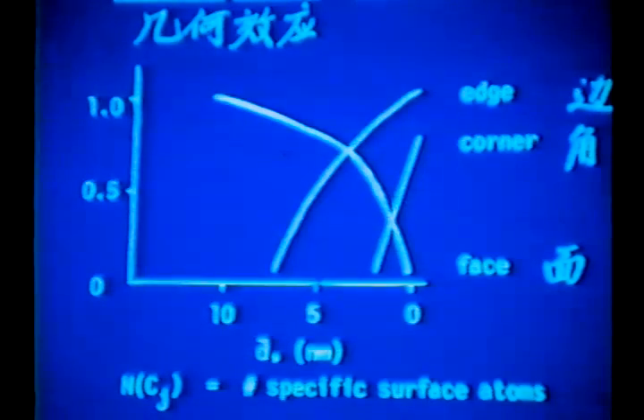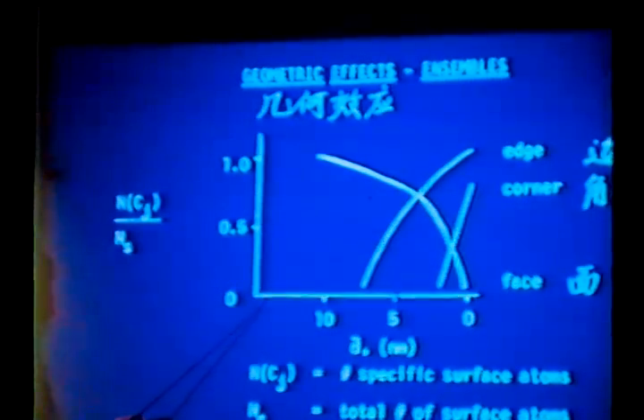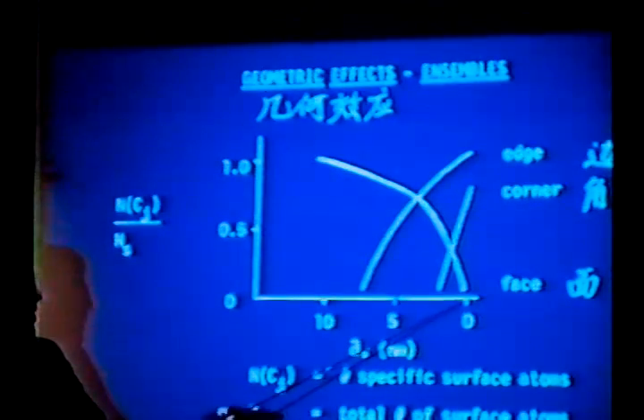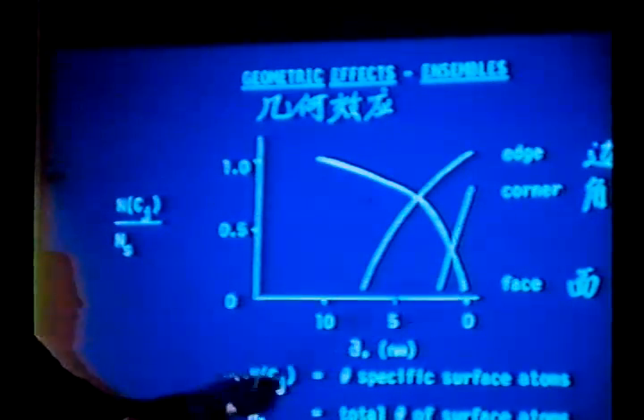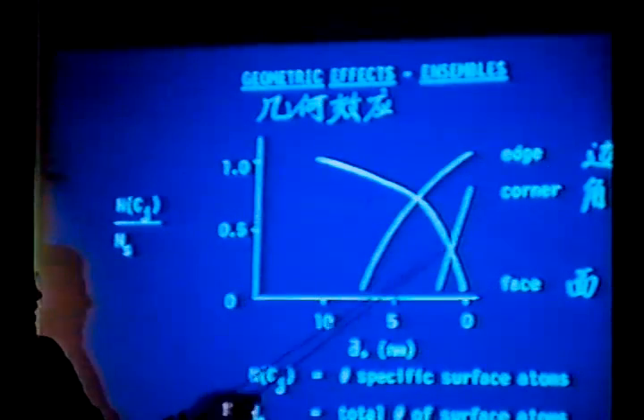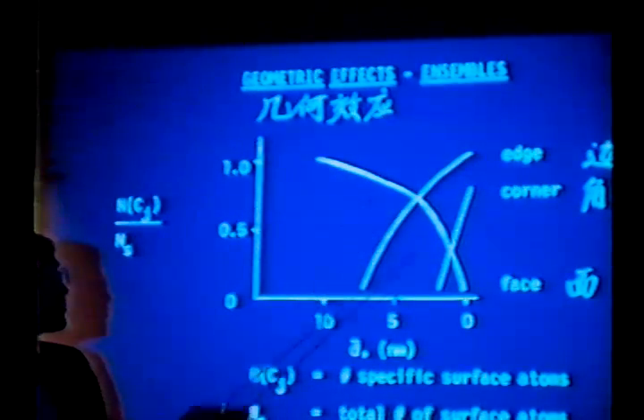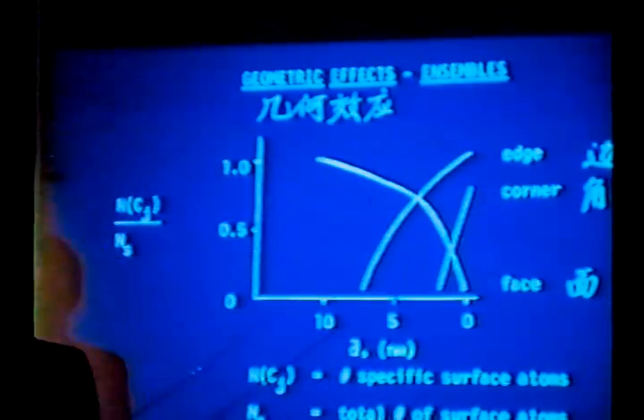And if we think about a face, if we break up that metal particle into smaller and smaller particles, we're going to get fewer and fewer face atoms. We're going to get more and more edge atoms and more corner atoms as we get a smaller and smaller particle size. This is sort of backwards perhaps, this is at very large particle size, this is small particle size. As we look at the number of face atoms, as we get smaller and smaller particle size, they go down. But the number of edge atoms and the number of corner atoms go up.